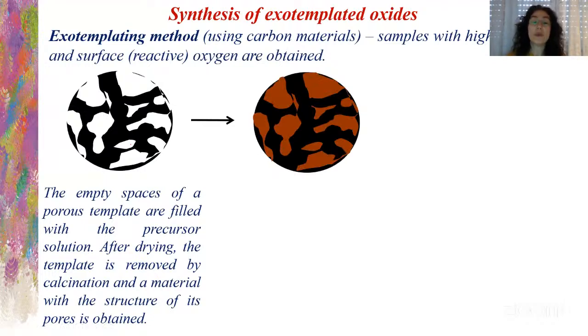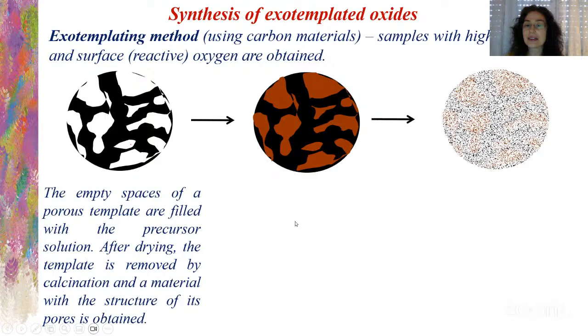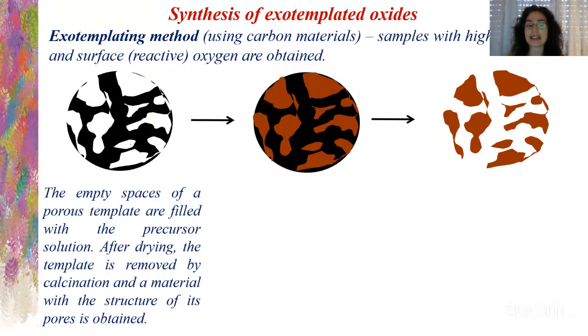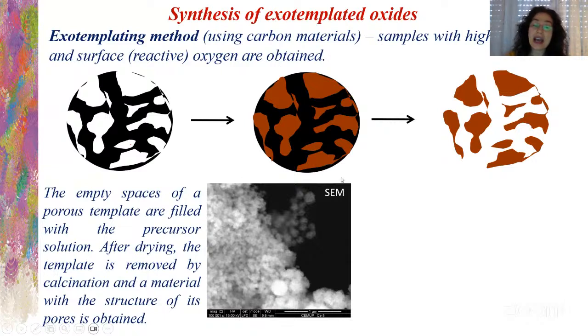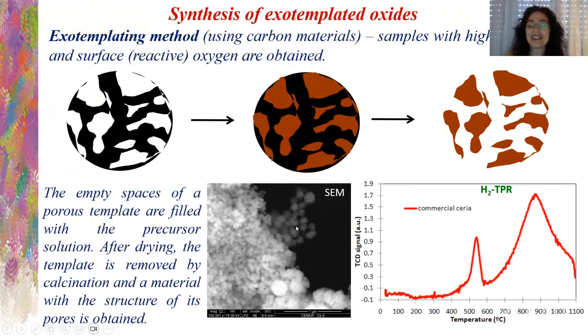Then what happens? We dry it, okay? And then the carbon template material is removed by calcination, okay? And then a material with the structure of the pores of the template is obtained. So it's like that. We have here the same image, and if you look closely, you can see little holes that were where the template was.